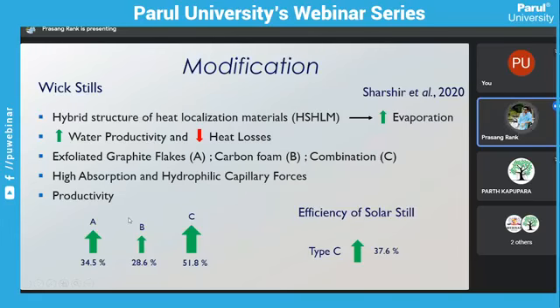So these two materials we can use to increase the evaporation or high absorption, and also hydrophilic capillary force. Due to the material's ability to capillary the water, the evaporating temperature will decrease, and also less amount of water we are keeping over the wick, so the efficiency will directly increase.